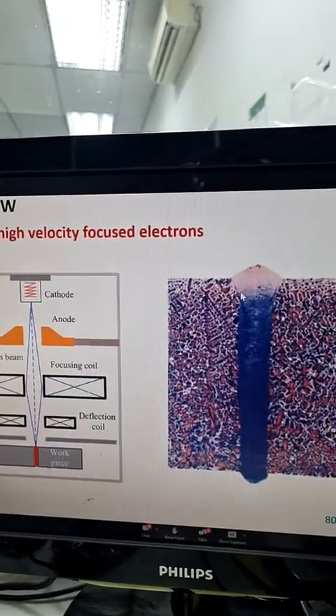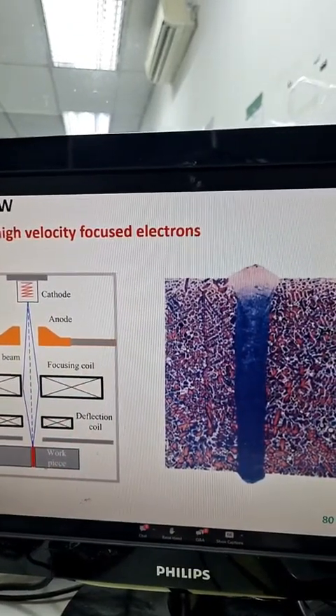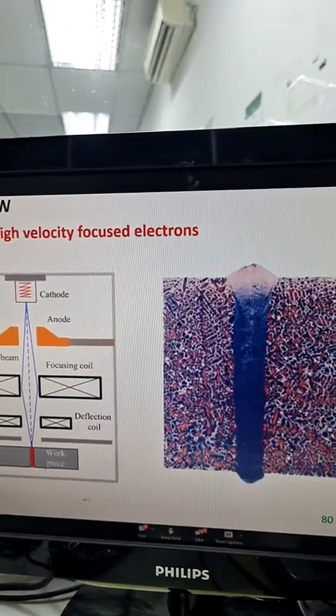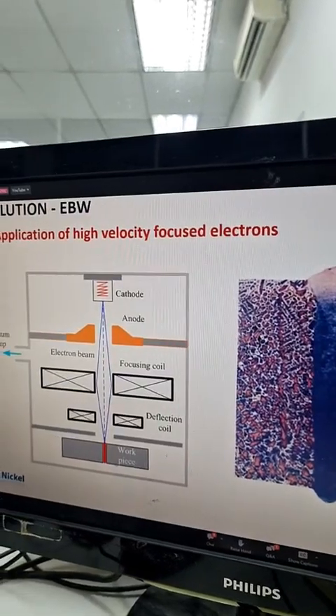The advantage is it's a very focused beam, and no filler is required. So your dilution is going to be very minimal because you are not adding any external filler wire here. Your weld will be much better when compared to your arc weld. You can see how the penetration comes in the case of electron beam welding. It's another high potential process which can be explored for dissimilar metal welding.